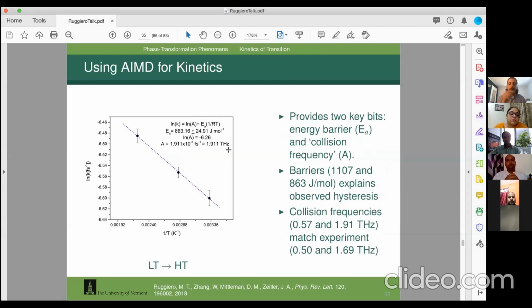We can do it in both directions, from high temp to low temp and from low temp to high temp. The predicted collision frequencies of 0.5 terahertz and almost 2 terahertz beautifully match the experimental frequency of that particular type of motion, that longitudinal translational type of motion. This is just showing everything is linked here. The vibrations are linked to the phase transition, and the phase transition is linked to the vibrations. It's a bit of a chicken and egg situation.